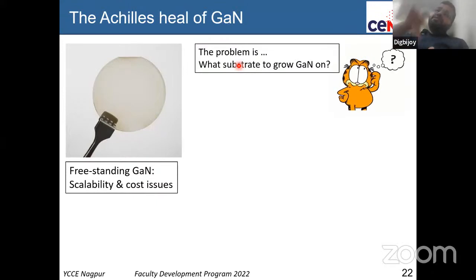However, when you try to grow it on a different substrate, the substrate on which you are growing is different from gallium nitride. So there will be mismatch issues. And those issues can lead to material defects because you're forcing gallium nitride to grow on a foreign material, which is not like gallium nitride. So there will be some issues at the interface, some defects will propagate, we call them dislocations, and this is inevitable. And those will reduce the performance of the device.